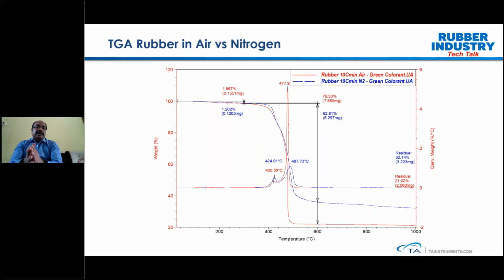And here another aspect is the atmosphere we are using. As all of us know, the decomposition of any polymeric material, whether it's rubber, polymer or thermoplastic, is basically a kinetic reaction, and that is purely dependent on the atmosphere we are using. In this case, we have taken the same rubber compound and tested it under air and under nitrogen. So what we see here is a clear change. The sample tested in air shows a faster decomposition as compared to the nitrogen atmosphere. This graph clearly shows that even though the rubber chemistry is the same, the atmosphere has a major effect which has totally changed the decomposition kinetics.